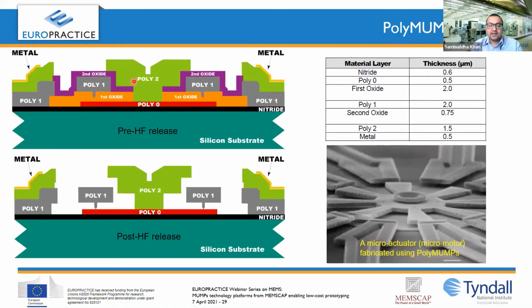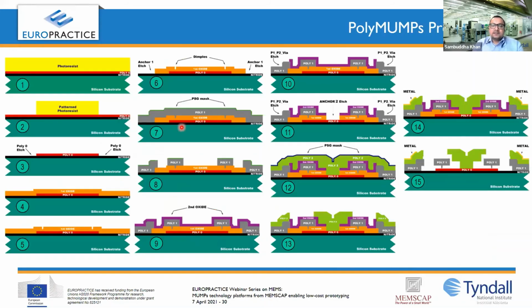After they deposit and etch all the layers, all the 12 masks, they go for the oxide removal, or the release of the device. Once the sacrificial oxide layers, the first oxide and second oxide, are removed, you can get floating devices. These are called dimples, which ensure that poly 1 doesn't stick to poly 0, and they can move freely because the contact surface area is small. So this is a complicated process. You can see it's like 12 processes.